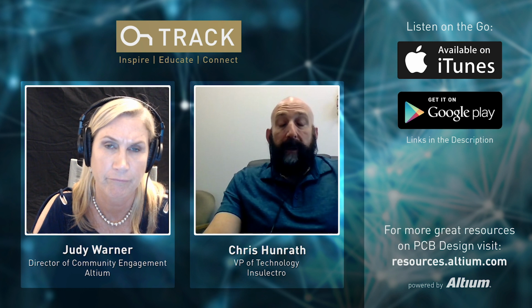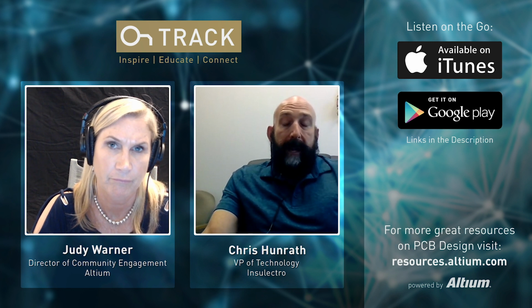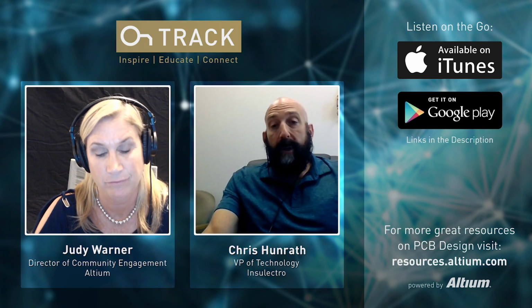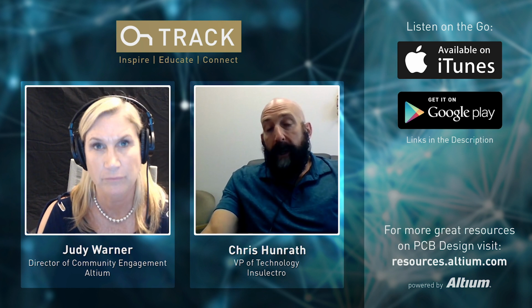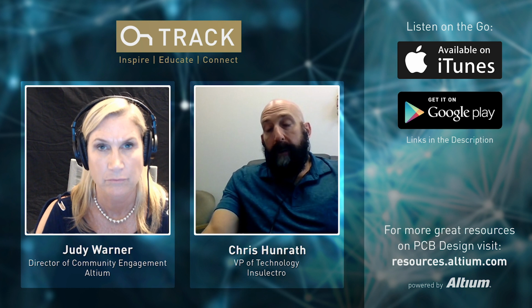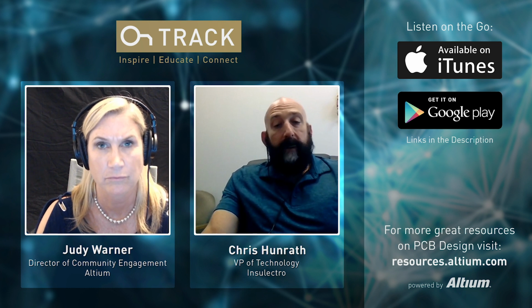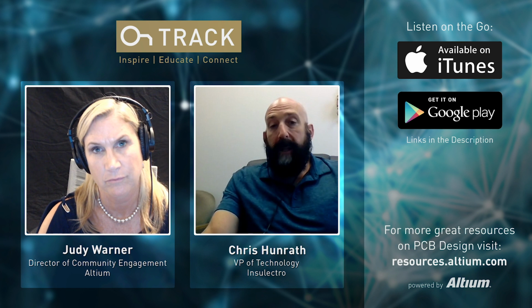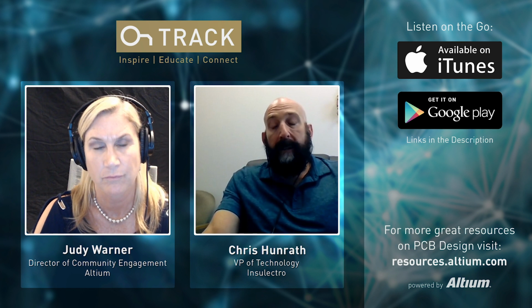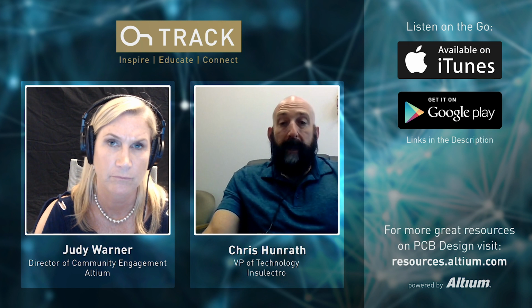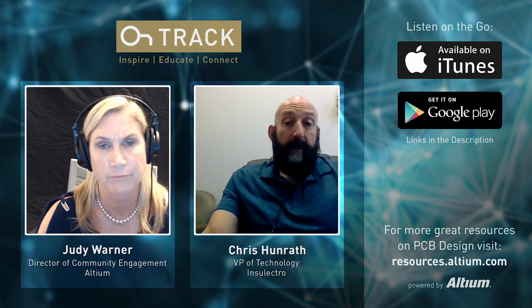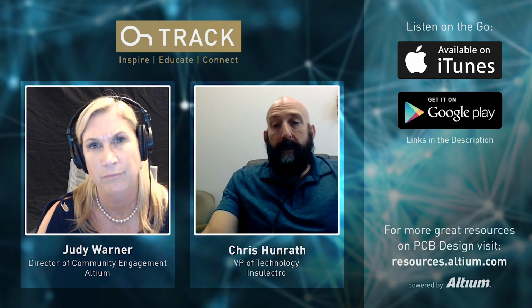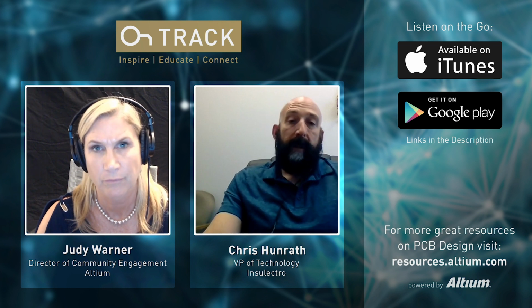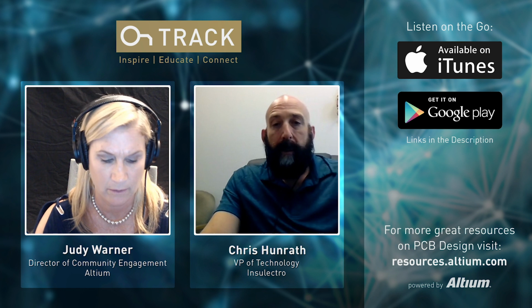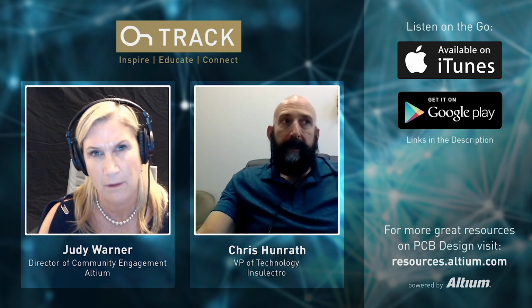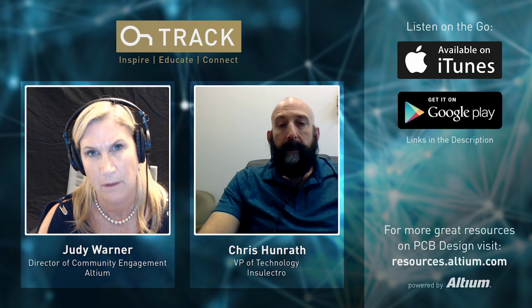So that's what interests us, because when a board's in use, it heats up. You have some z-axis expansion. With other types of paste interconnects, you have a resistance change every time the board is heated, even from, let's say, 40, 50, 60 Celsius in normal use, not even in any kind of harsh environment. Right. Parts of the board would heat up from the components, and you'd have a change in resistance. And that's what this is designed to circumvent, because it forms that metallurgical bond with the copper interlayers. Interesting. So it is a different technology than the paste you would use in printed electronics. Okay.